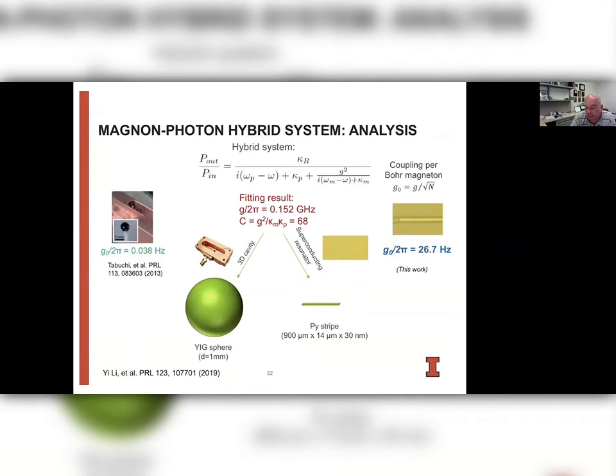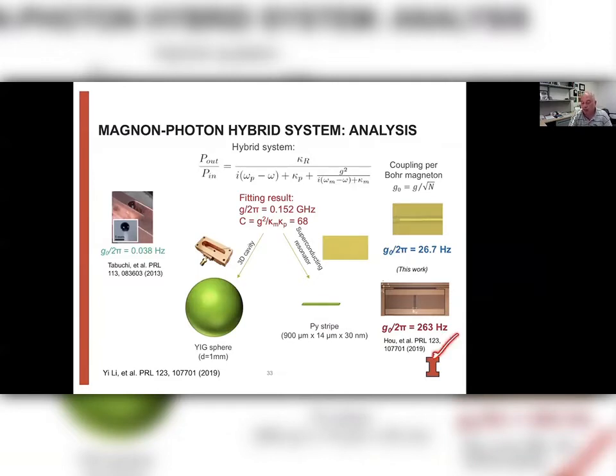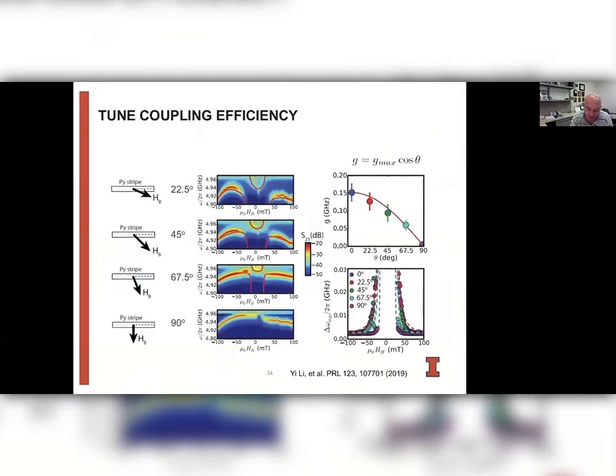And one of the reasons is that in our case, the filling factor of the magnetic structure within the complete volume of our resonator is much larger. And so that allows for getting much stronger coupling. In fact, one can optimize this even further. And this was nicely shown within the group of Luqiao Liu at MIT, who used a similar approach of using a superconducting resonator with permalloy, except they used a lumped element structure, which allowed them to have a coupling per spin that's even an order of magnitude higher than what we had in our structure. So this shows that by further optimizing the resonator design, there's actually still quite a bit of room for improvement for these types of devices.